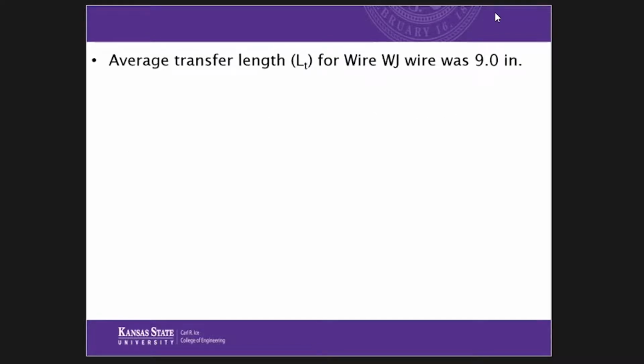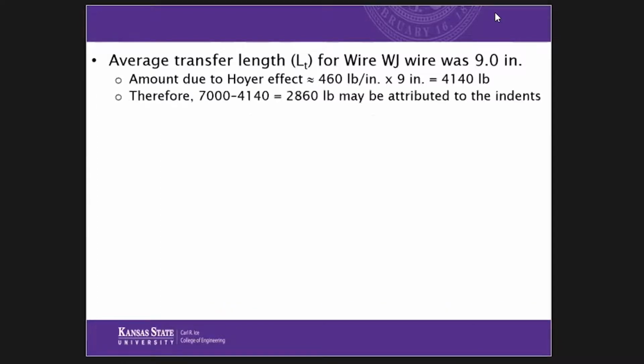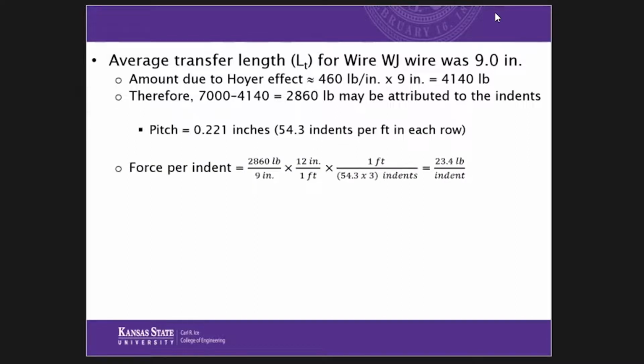Now, if we consider the wire WJ that had a medium depth indent, that transfer length was 9 inches. Well, if we assume it has the same frictional characteristics for the steel, then over that same 9 inches, we get about 4,140 pounds that we could attribute to friction. So the remaining 2,860 pounds has to be due to the indents. And on that particular wire, the pitch, the spacing of the indents, was 0.221 inches, which means if I take 1 over 0.221, multiply it times 12, I get 54.3 indents per foot in each row. There's 3 rows. So I can convert that to a force per indent then of 23.4 pounds is the force being attributed to each individual indent.